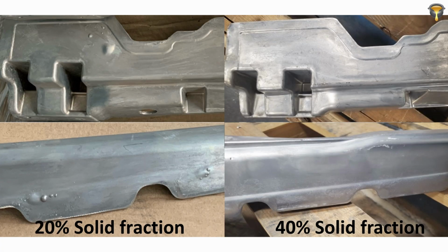We will show it on the screen: for 20% solid fraction, you have that turbulent fill, you have entrapped air, and in the heat treatments you have blisters. Then going back into the melting furnace, at 40% solid fraction, you have that perfectly laminar fill of the casting, and that's what you want. And so you need a process that absolutely gives you the same condition every time, and that's the RheoMetal process with its enthalpy exchange mass, which makes it the only process that is not temperature controlled, it's enthalpy controlled. And I think, Staffan, you can tell us more about that process.